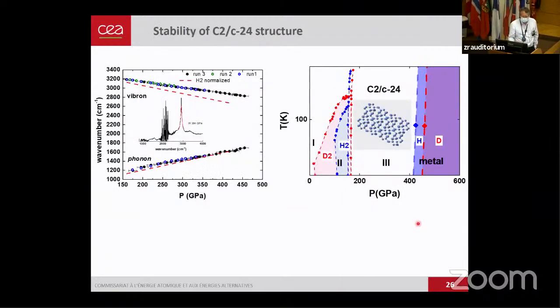We also observe the same signature of the vibron and phonon, and so it's the same structure. So H2 and D2 are compressed in the same structure. And what's interesting is that if you normalize the vibron measurements of hydrogen by the square root of the mass compared to deuterium, it seems that hydrogen is lower. So there is more softening of the hydrogen molecule than the deuterium molecule, which could explain why metallization occurs earlier for hydrogen than deuterium. For the phonon, they almost agree, so this is working very well, as expected.